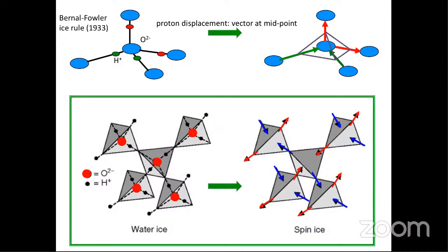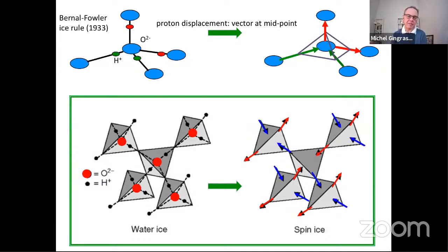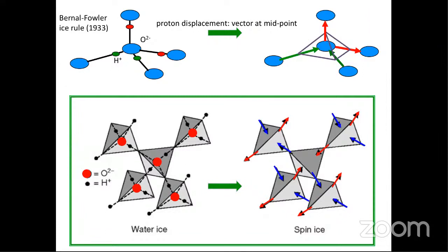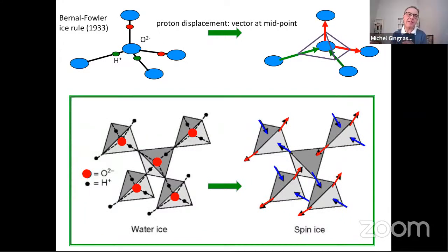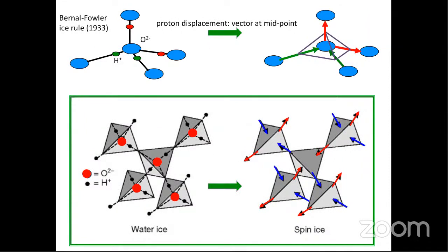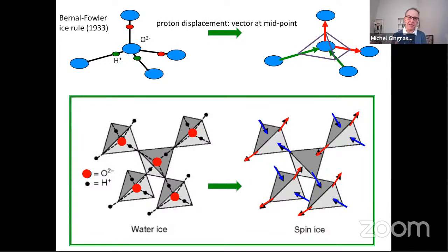And so these vectors pointing in and pointing out in spin ice correspond to the direction of the Ising moments, with the displacement of the protons being really discrete, either that much in one direction or the equivalent distance towards the other protons. So at the nearest neighbor level description, the partition function for water ice would be the same as spin ice. There's a complete isomorphism in a sense between spin ice and water ice. The partition function and the thermodynamics are the same, but also the spin directions in spin ice map, in a sense, the proton configuration for water ice. And that's why it's called spin ice, and it's also part of why it's attracted so much interest.